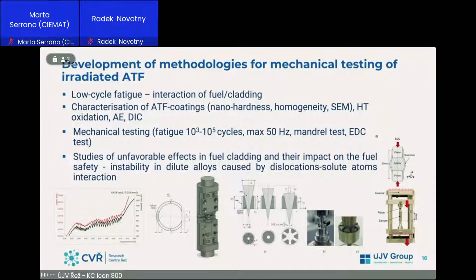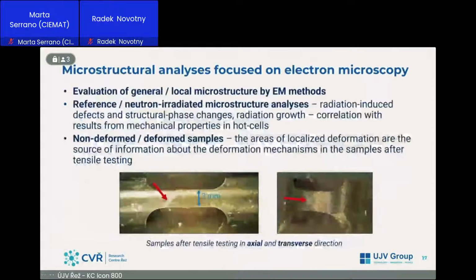Regarding the testing of ATF claddings, we developed within a few projects the new methodology. So we do on ATFs the low cycle fatigue. We characterize the ATF coatings by nano hardness and SEM by wave dispersive spectroscopy. So we notice the chemical changes and local mechanical changes in the ATF coatings after neutron irradiation. And as well, we study some unfavorable effects in fuel claddings and their impact on the fuel safety. So here are the several new methods we developed under the TACHE project.